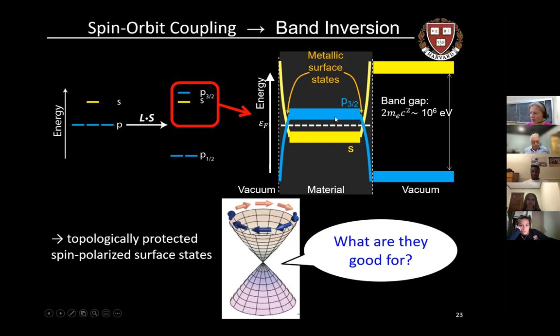Another way of thinking about that is that the topology of the surface is determined by the band ordering of the bulk. So if your bulk is too small, then it doesn't have a well-defined band ordering, and you're therefore not going to have a topological surface state. So in practice, this dimension is often on order a few nanometers, like 3-4 nanometers.